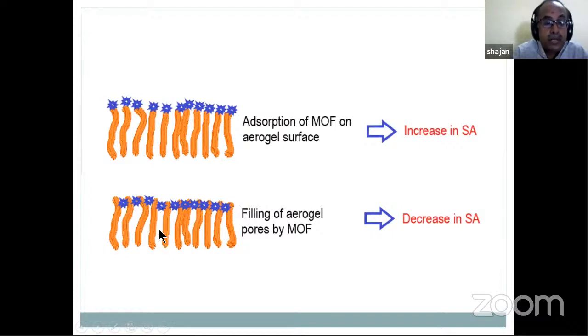You cannot go inside the pore. While calculating, you are passing the nitrogen. Nitrogen will not go into these pores. It will be moving along these areas, and that is why the surface area is decreasing. It is for nickel BTC that it is decreasing.